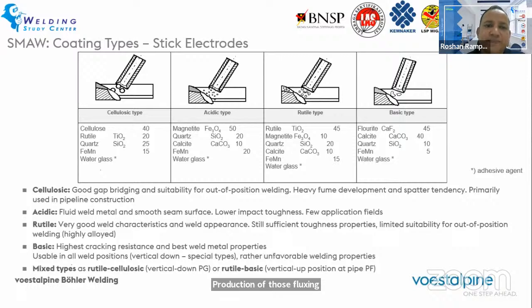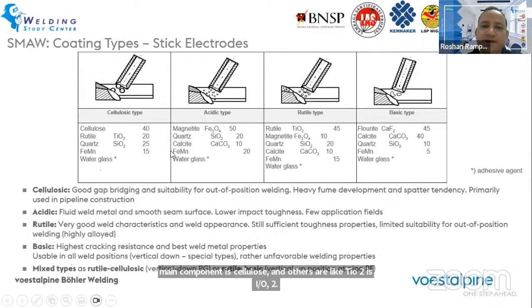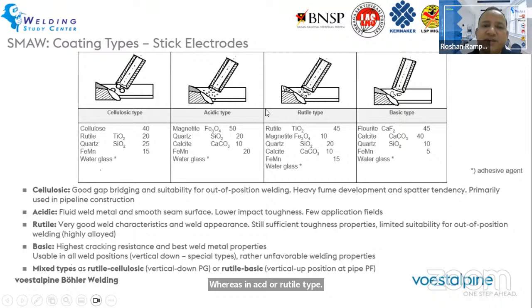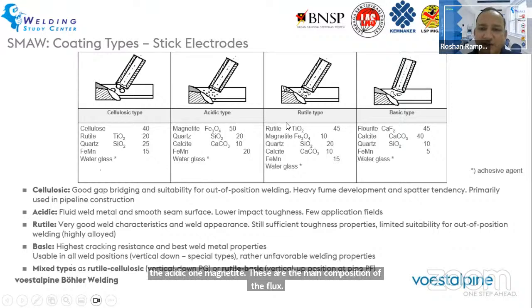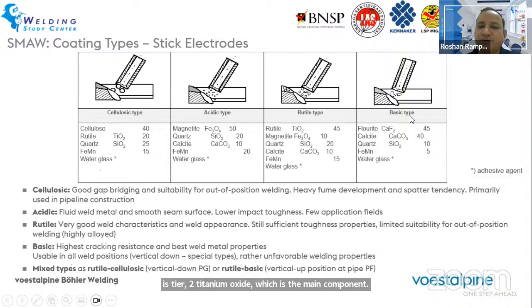So cellulosic type is the one, another one is acidic, or also similar is the rutile type, and another one is basic type. So in cellulosic type, the main component is cellulose, and others are like TiO2, SiO2, FeMn. Whereas in acidic or rutile type, in the acidic one, magnetite, quartz are the main composition of the flux. Rutile is nothing but titania, which is TiO2 titanium oxide, which is the main component. And another is the basic type, in which the basic flux components are in higher proportion, like CaF2 and CaCO3 are the main components for basic type.